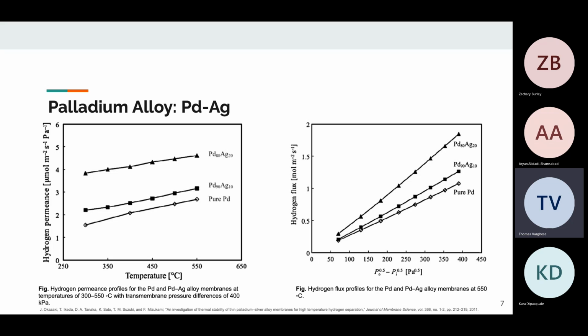The figure on the left shows the hydrogen permeation for pure palladium and palladium-silver alloy membranes at temperatures of 300 to 550 degrees Celsius and with a pressure difference of 400 kilopascals. Overall, the hydrogen permeation increased as the testing temperature increased, and the hydrogen permeability was significantly enhanced by alloying with silver.